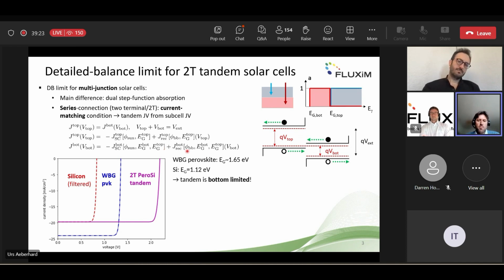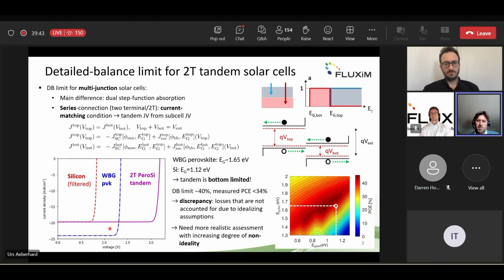If we do that for perovskite with a band gap of 1.65 electron volts and the standard silicon band gap, we find that the tandem is quite severely bottom limited. So it's the silicon that limits the conserved current here. This configuration is not in the sweet spot of the detailed balance limit, but it gives around 40%. However, we have seen that currently the record efficiencies are rather in the range of 34%.